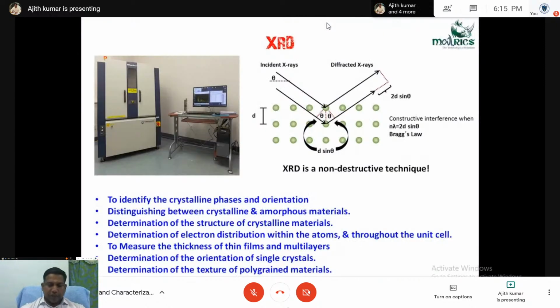After processing, that means after metal processing like metal casting, powder metallurgy, or 3D printing, the first characterization technique is XRD. From XRD we can get the different phases present in the metal. Not only that, we can distinguish between crystalline and amorphous material, determine the structure of crystalline material, determine electron distribution within the atom and throughout the unit cell, measure the thickness of thin films and multilayers, determine the orientation of single crystals and the texture of polygrained materials, and measure strain and small grains using XRD.